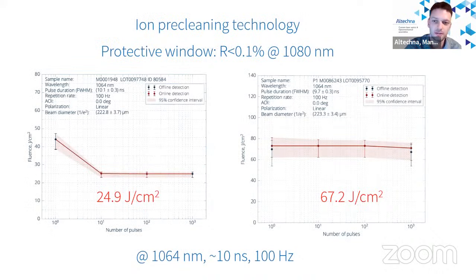After many trials and failures, we were able to achieve great results for transmissive optics. I will present just two examples. The first one is a window coated with an anti-reflective coating. Without ion pre-cleaning, typical LIDT values are somewhere around 25 joules per centimeter squared. Meanwhile, with pre-cleaning technology, we repeatedly managed to achieve more than 67 joules per centimeter squared. Damage threshold tests were done at 1064 nanometers, so the increase was more than 2 times.